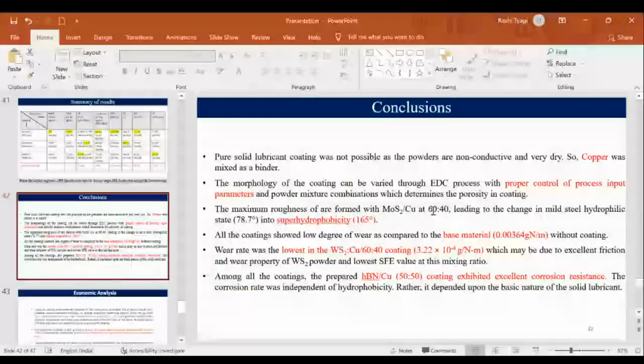So the conclusion that we can get: pure solid lubricant coating was not possible. So we have used the copper powder, because copper powder was conductive and it works as a binder, because all the other powders are semiconductors. So we can only perform the EDM operation at high conductivity. So we have used the copper powder as a binder to mix it with the solid lubricant. By controlling the input process parameters, we can reduce the porosity in the coating.